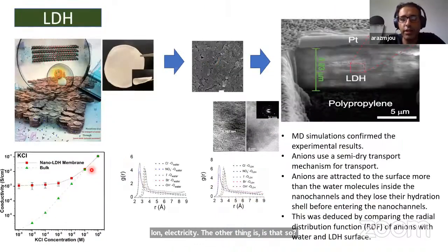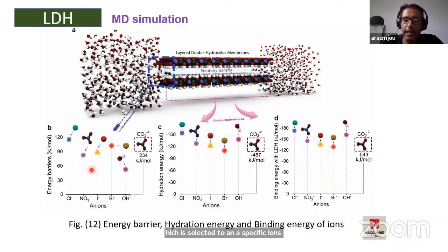LDH is a very interesting family of 2D materials, but we found that we can induce the regular deposition or self-assembly formation of the LDH layers in order to create nanochannels with a specific surface chemistry which is selective to specific ions. And again, similar to MXene, there is always a sort of energy barrier, hydration energy, and binding energy. There is a competition between the entry energy barriers, hydration energy, and binding energy that you can play around with to make your membrane lithium or any sort of ion selective membrane.